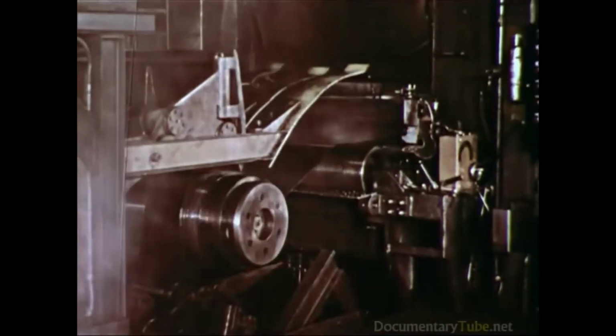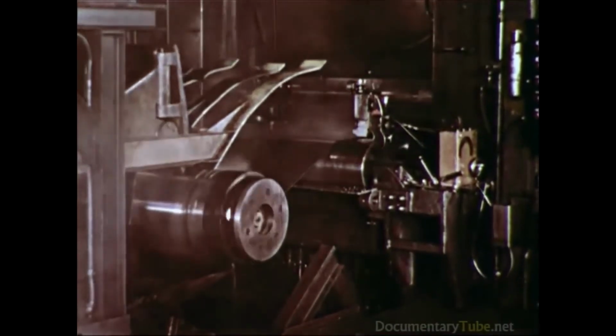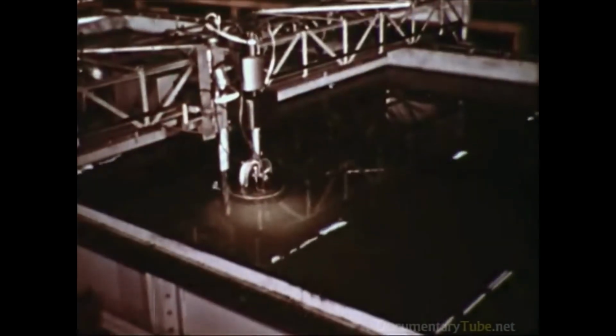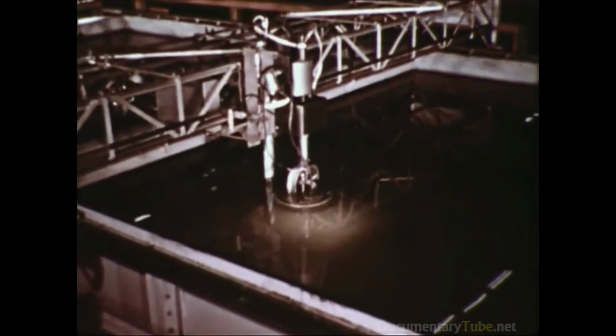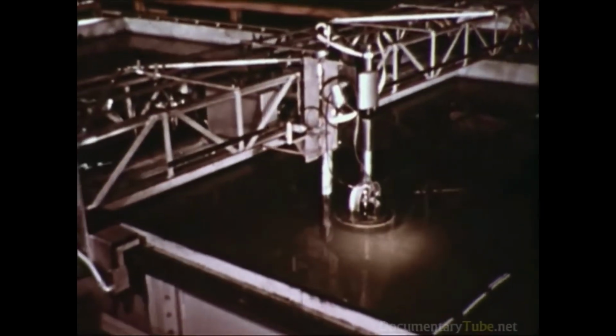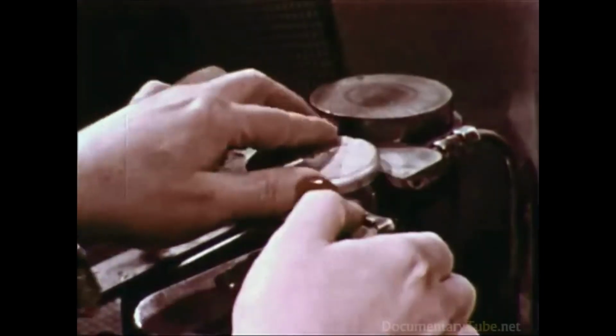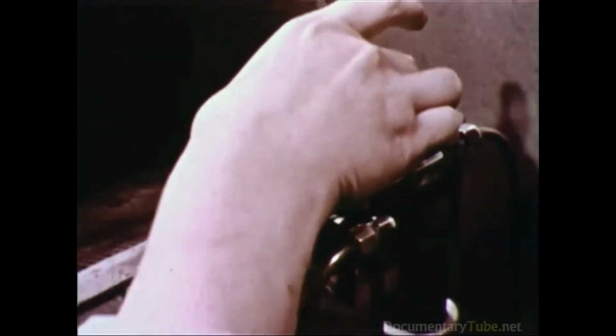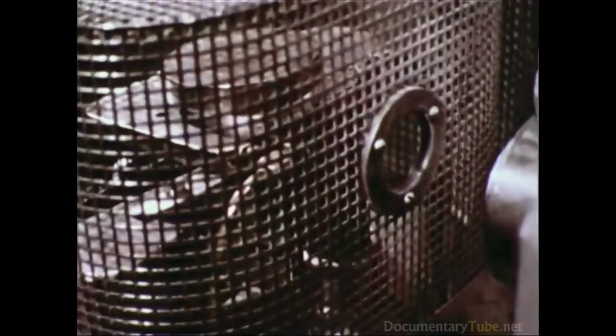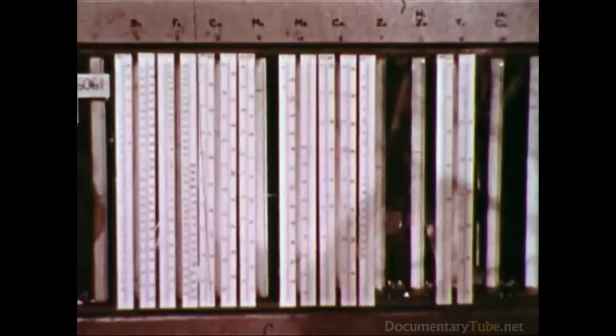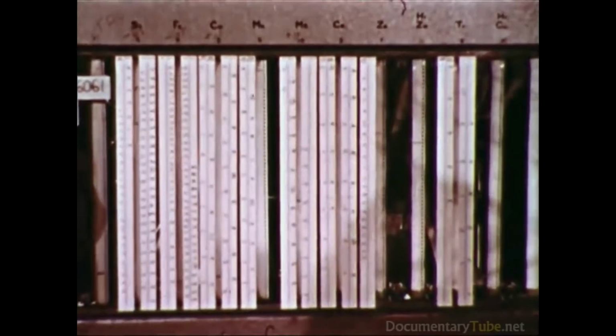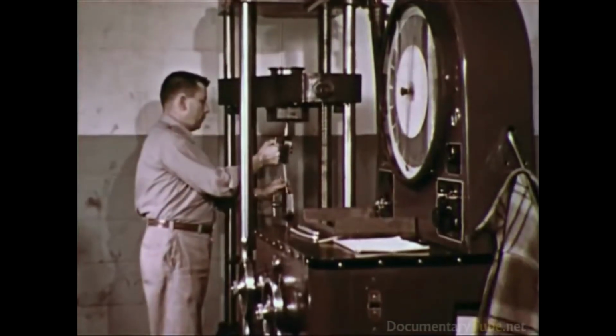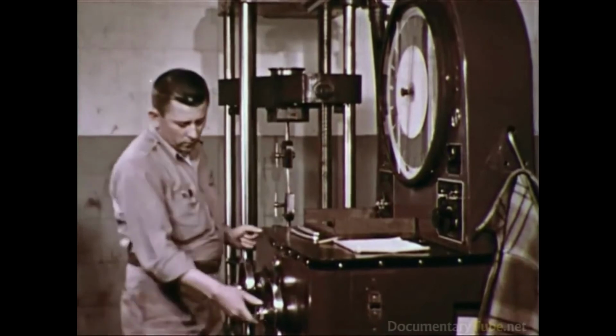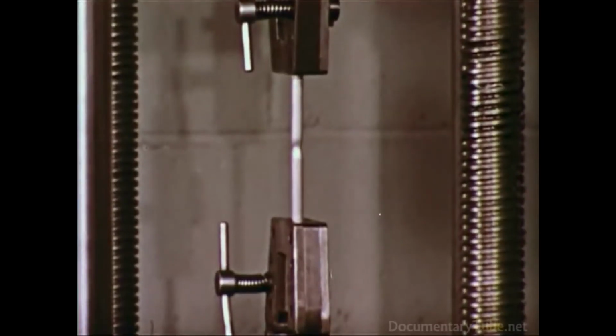For example, a flying micrometer keeps sheet gauge within the most minute of tolerances. Ultrasonic waves scan heavy plate and billets for internal flaws. Should any exist, they are revealed on the electronic screen. And the alloy content of the metal itself is analyzed by direct reading spectrograph, called a quantometer. These quality control procedures help sustain the high standards which fabricators and the public have always associated with aluminum products.